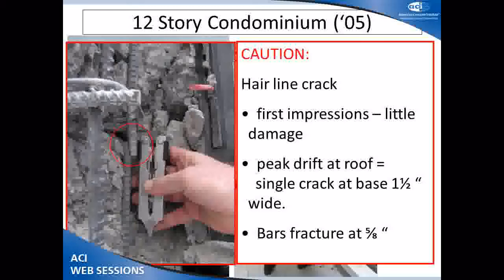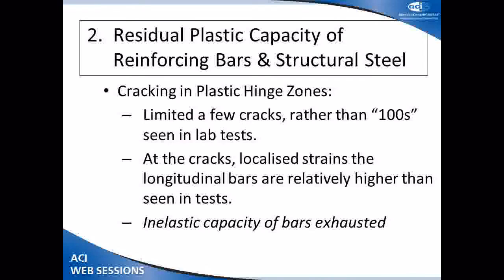What we found, as first impressions, is that cracks meant there's no damage. I believe there's a recommendation in FEMA that if a crack in the wall is less than 5 mils, just epoxy it up. I'm not so sure that that's a good tactic to take at the moment. We have another way of dealing with this, which I'll talk about in a moment. We found that the peak drifts at the roof led to that single crack at the base of the wall opening up about 1.5 inches. And we know that these sort of bars fracture at 5/8 of an inch, so they didn't have a show of surviving.